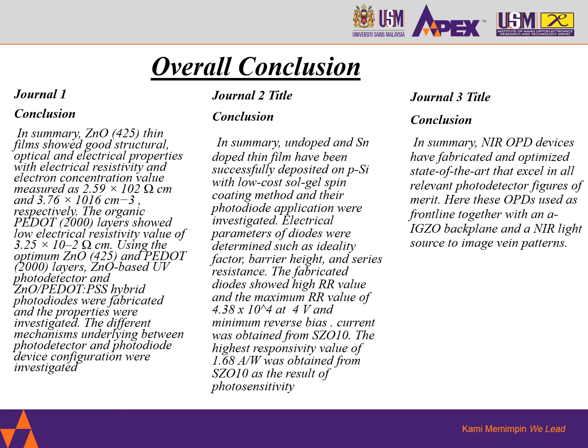From journal 2, the conclusion is, in summary, undoped and tin doped thin films have been successfully deposited on p silicon with the low-cost sol-gel spin coating method and their photodiode application was investigated. Electrical parameters of diodes were determined such as ideality factor, barrier height and series resistance. The fabricated diode showed a high RR value, with a maximum RR value of 4.38 × 10^4 at 4 volt, and minimum reverse bias current was obtained from SZO10. The highest responsivity value of 1.68 A/W was obtained from SZO10 as the result of photosensitivity.